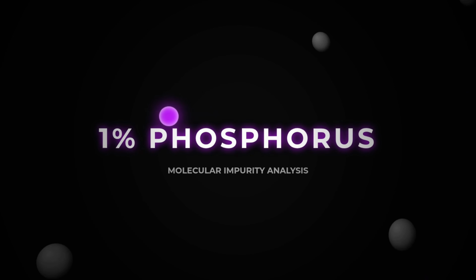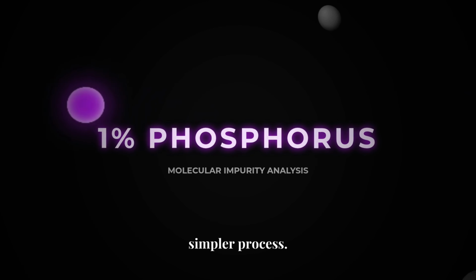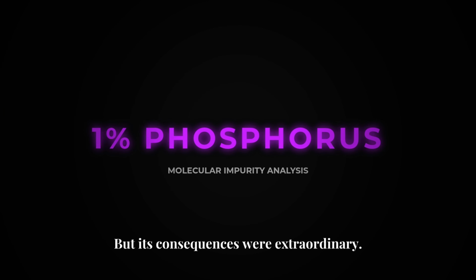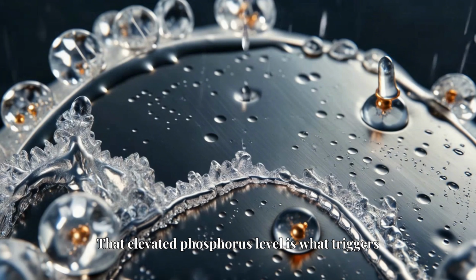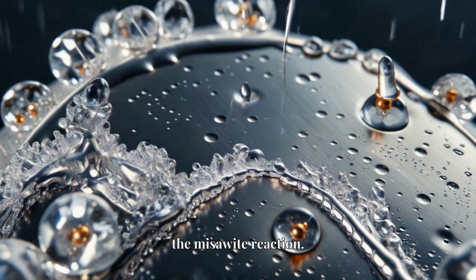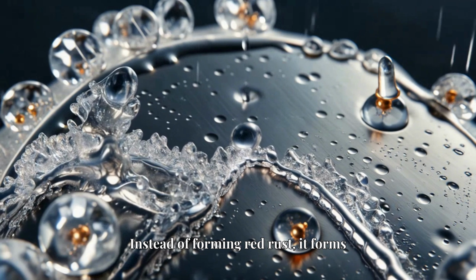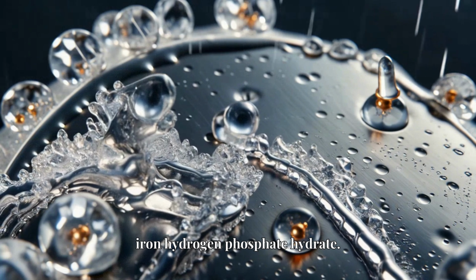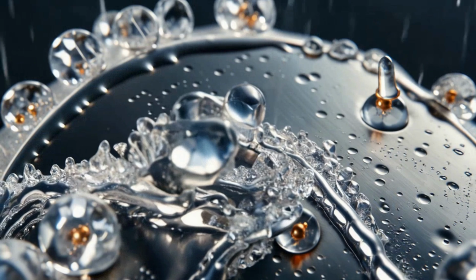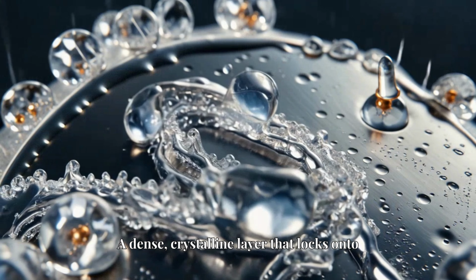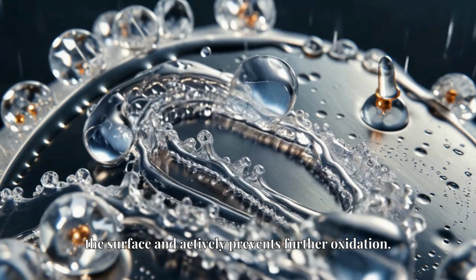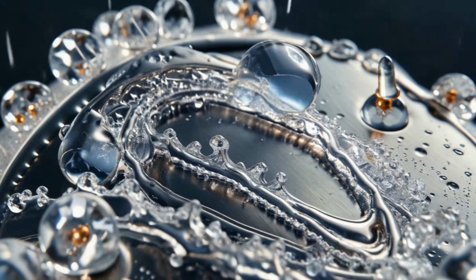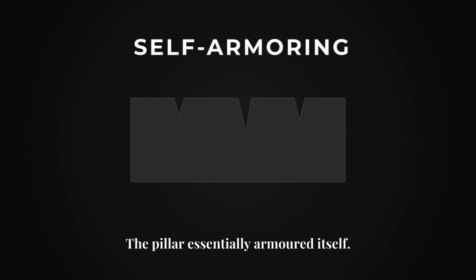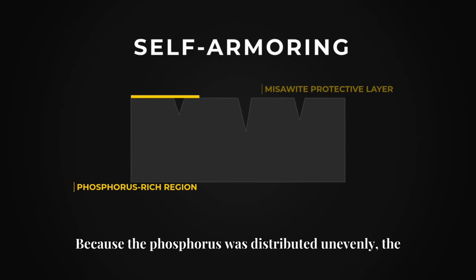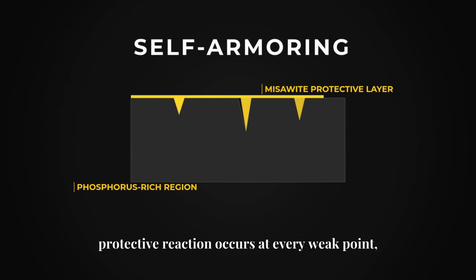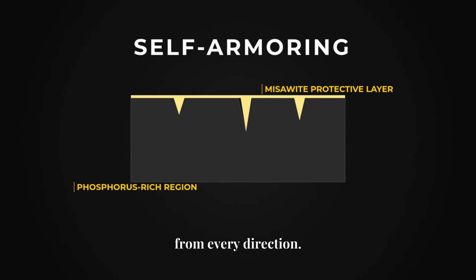This wasn't an advanced discovery. It was a side effect of a simpler process. But its consequences were extraordinary. That elevated phosphorus level is what triggers the misawite reaction. Instead of forming red rust, it forms iron-hydrogen phosphate hydrate, a dense crystalline layer that locks onto the surface and actively prevents further oxidation. The pillar essentially armored itself. Because the phosphorus was distributed unevenly, the protective reaction occurs at every weak point, from every direction.